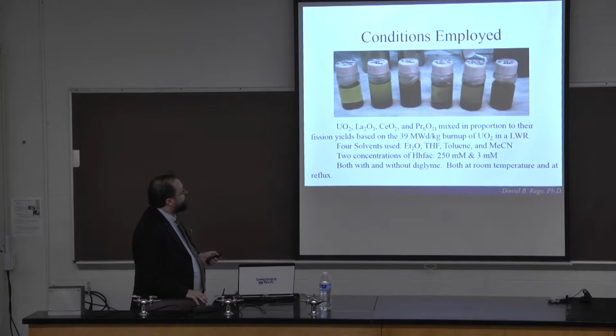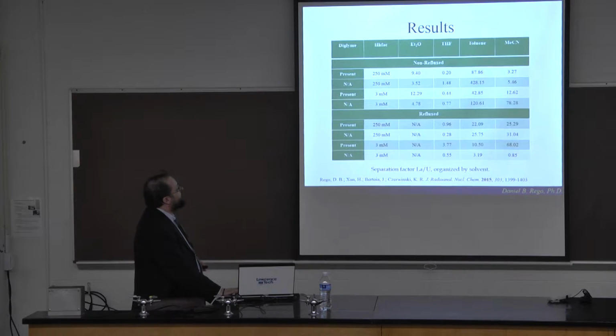Use various solvents to see which one would work best: ether, tetrahydrofuran, toluene, nitrile, 2 concentrations of Hhfac, enough to hypothetically react with all the oxides, or enough to react with just the lanthanides, both with and without diglyme, at room temperature and at reflux. It turns out that the one major factor that changes things is the solvent.